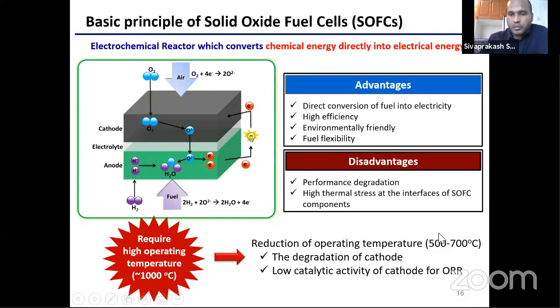Another disadvantage in reducing the temperature is that the catalytic oxygen reduction activity goes down. When temperature is high, the oxygen reduction reaction (ORR) will be very high—that's the rate limiting step. When decreasing the temperature, oxygen reduction reaction undergoes degradation, and this rate limiting step becomes even higher.